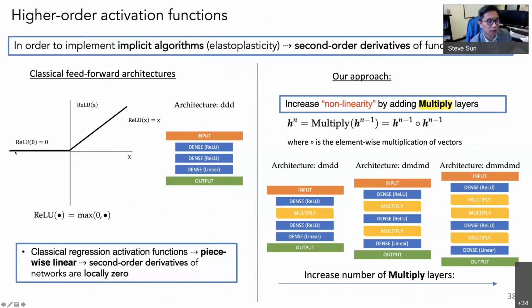We have ReLU activation functions. You see that corner here, if you take the derivative, you will get a jump. So it doesn't have enough continuity for us to take the second derivative to obtain the tangent. However, we can introduce a multiplying layer so that the layer multiplies itself times itself, and that would increase the differentiability, and then we can control the degree of the continuity such that we can obtain a smooth tangent. So this is just a small trick.